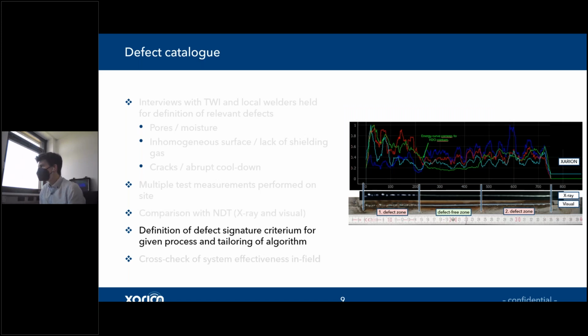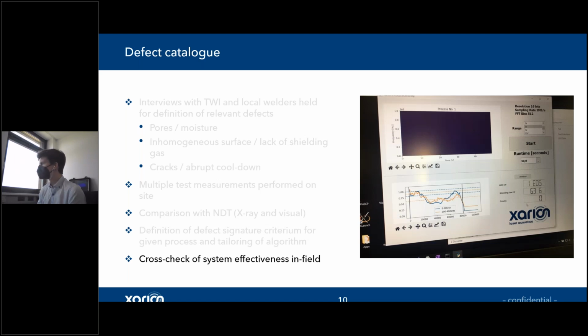Here, for instance, we showed the comparison of our signals to the defect, and what we employed was different criteria for each of the 3 defects mentioned previously. So each of these defects has a certain signature in a different frequency band, and that's what we found out there, and we tailored our algorithms to find these 3 defects in 3 different, actually 4 different frequency bands. And then we did a cross-check in the field to see how well it really detects all the defects that we set up.